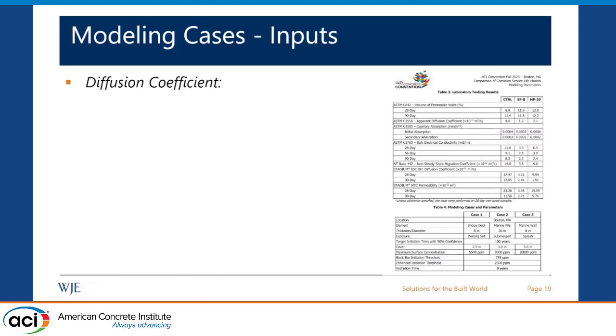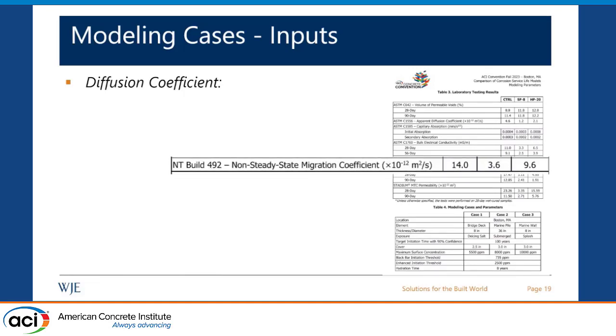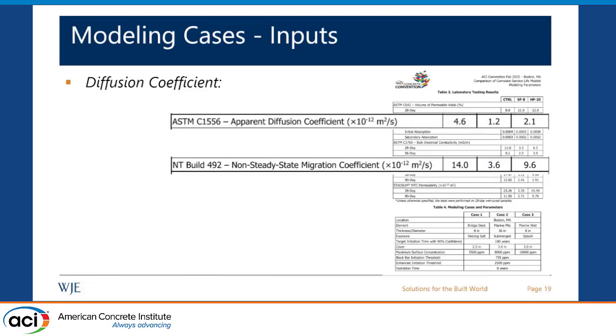So for the diffusion coefficient, we were given results using NT Build 492, and also bulk diffusion test results, C1556. And based on our extensive experience with project work, we found that NT Build 492 tends to give us conservative results relative to the diffusion coefficient. And based on that, the apparent diffusion coefficient provided us with more representative values. So in all the results that I'm going to show after, we are relying on the results from ASTM C1556.